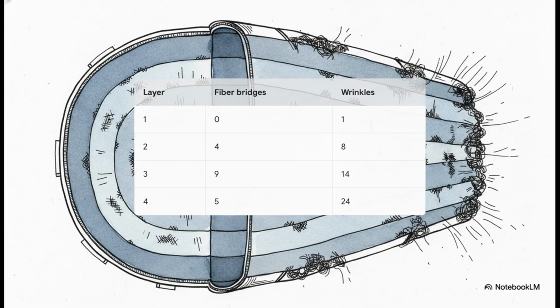It maps out these defects layer by layer, starting from the inner layer, layer 1, and moving outward to layer 4. It's literally a countdown to disaster. Notice how the wrinkles jump from just 1 on the first layer up to 8, then 14, all the way up to 24 wrinkles on layer 4. These manufacturing anomalies aggressively multiplied as they built the hull outwards. The geometry of the entire structure was inherently destabilizing itself during the fabrication process.